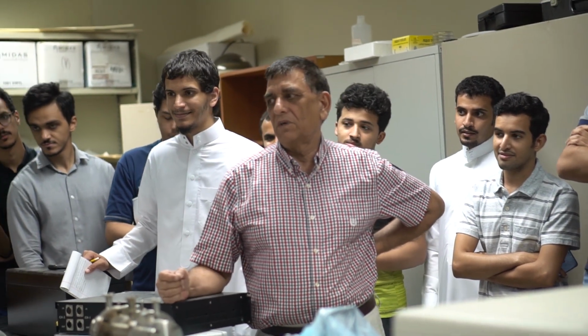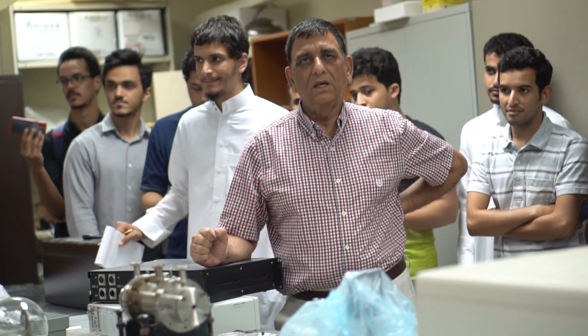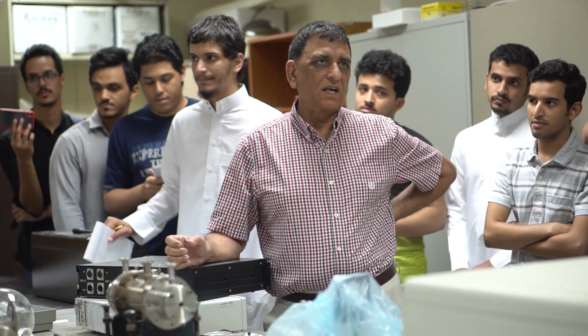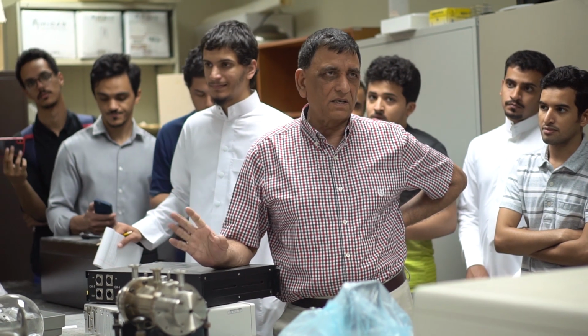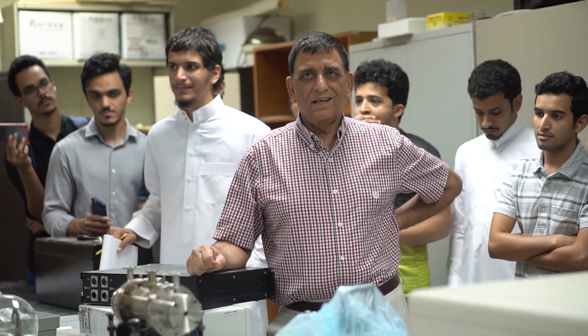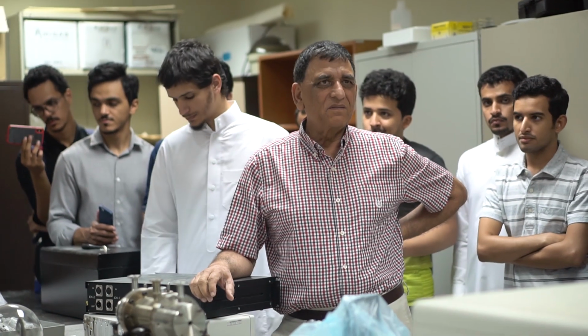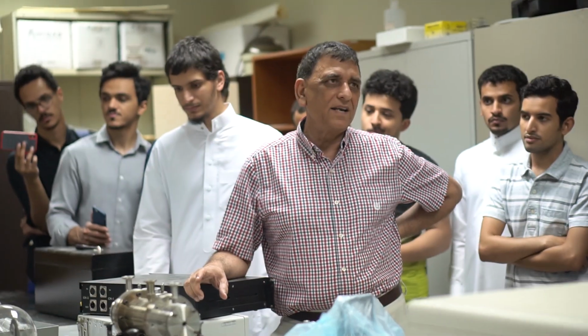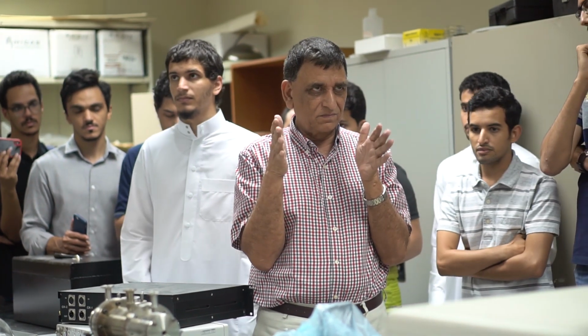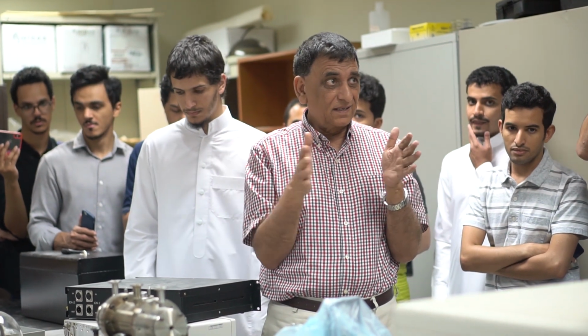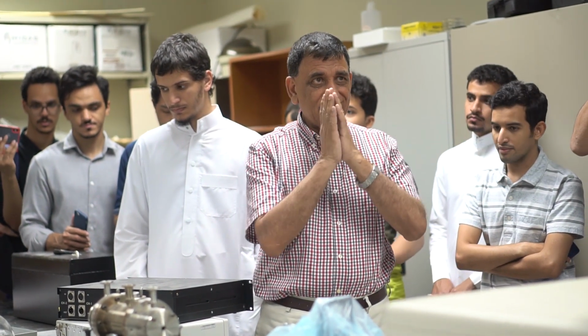So this excimer laser is basically built on the principle that we mix argon and fluorine gas. Fluorine is F2, a stable gas, it doesn't need any electron. Also argon doesn't need electrons. But when we put these two gases in a high electrical discharge, we have two electrodes and we apply a very short nanosecond pulse, around 28 kilovolt, electrical pulse. Then a discharge is created in the gas in between,